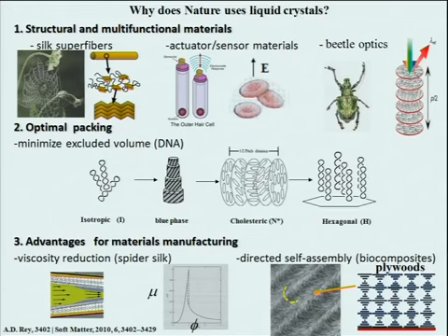At low concentration, we have an isotropic state. At higher concentration, we go to a blue phase, which is a double helix in two orthogonal directions. At higher concentrations, we have a cholesteric phase, and at even higher concentration, we have a hexagonal phase. So at very high concentrations, the demand is to exclude the volume, and so this hexagonal phase does the job.